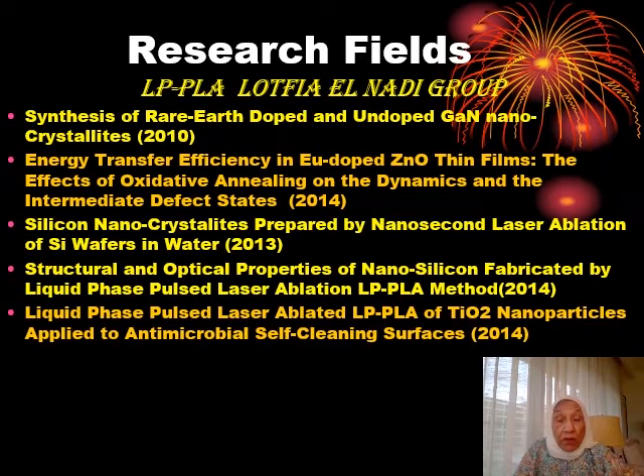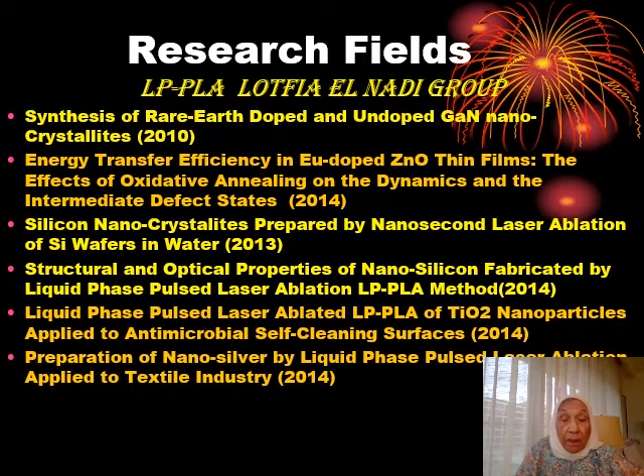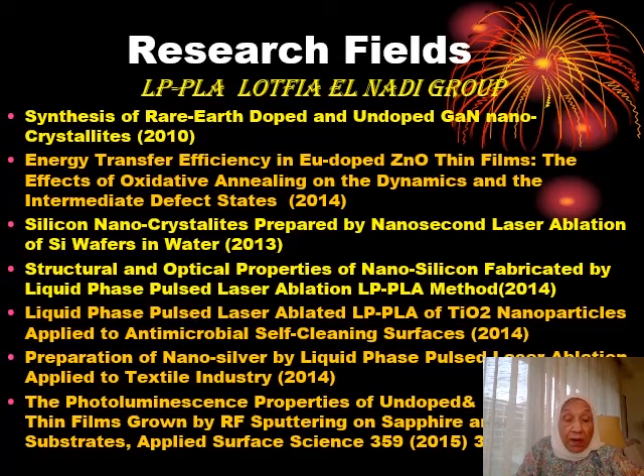In 2014 also we did some work on titanium oxide nanoparticles applied to antimicrobial self-cleaning surfaces. And we prepared nanosilver by liquid phase pulsed laser ablation applied to the textile industry in 2014. In 2015, we did some research work on photoluminescence properties of undoped and doped thin films grown by radiofrequency sputtering on sapphire substrates applied to surface science.